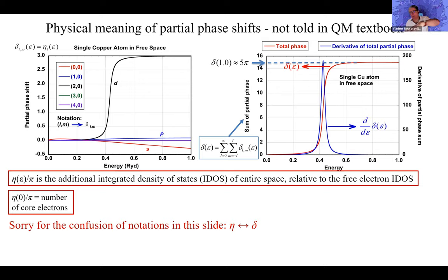Can we just say that if you take one cell, and zero outside, and solve it, you find the bound state? Then you add other cells. What will happen is that these bound states coming from different cells will start overlapping, and they will broaden into bands. That's the reason why these are all bands. This distinction between bound states and scattering states becomes blurred in a periodic solid. In a single cell case, it's not blurred.